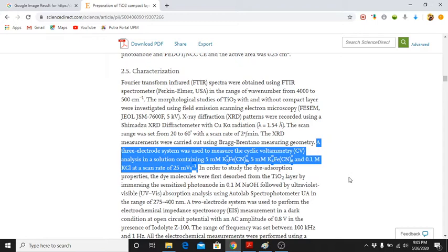If you study the recombination effect, I already explained in another video that the recombination effect has three routes. The first is recombination of the electron of the dye with the D plus, the oxidized dye molecule. The second route is recombination of the electron of TiO2 with the redox electrolyte, and last but not least, recombination between the FTO substrate, our TCO, transparent conductive oxide, either FTO or ITO, with the redox electrolyte. So the third route of recombination can be prevented by having a compact layer. Then by developing a compact layer, we can test our material. Is our material capable of fully covering the surface of FTO to avoid unnecessary recombination or not?